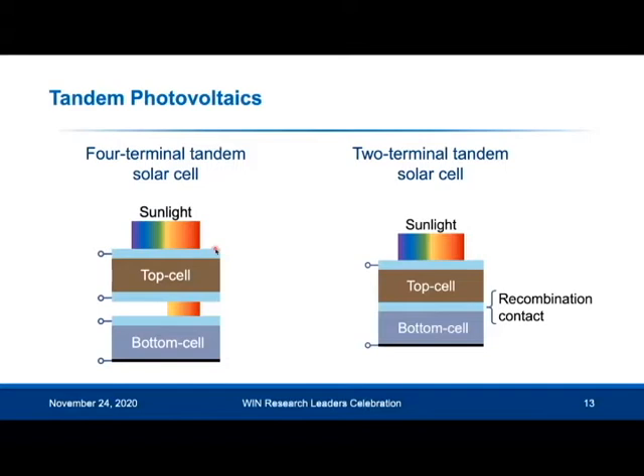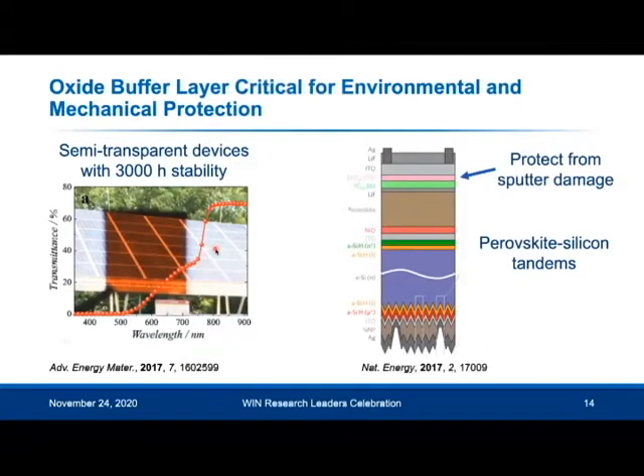And usually this electrode would be a transparent conducting oxide, for example, indium tin oxide. And this would usually be grown by sputter deposition. Now, sputter deposition is a very high energy process. So when you are sputtering something, you have very high energy atoms which are colliding with your substrate, in this case, the perovskite device. And because the perovskites and the organic charge transport layer are quite soft materials, you can easily damage these 2 layers. So we have to have an oxide layer, a buffer layer, which protects the perovskite top cell.